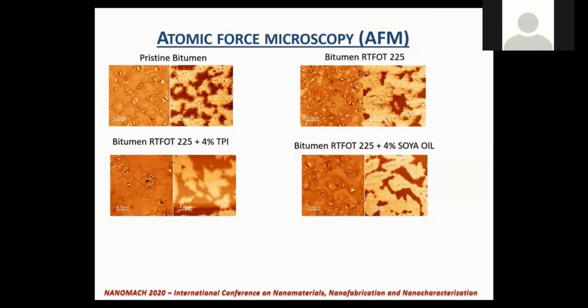In the phase figures, it is observed that the soft part of the sample, the dark part, is higher in pristine bitumen than in aged bitumen, where the clear part, the hard zone, prevails. This is due to the oxidation of the bitumen during the aging process.